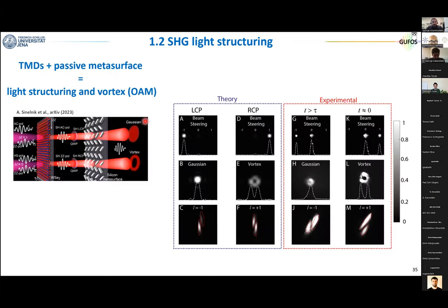And it turns out, this is something that we did in collaboration with Isabel Staude in Jena, that if you have an ultra-fast half-wave plate, that is our TMD in the nonlinear optics regime, and you combine it with a passive metasurface, then this total optical element can be used to tune the wavefront of light. So now we can play with this device to achieve on an ultra-fast timescale beam steering, Gaussian to vortex beam tuning, but even tuning of the orbital angular momentum. So these nonlinearities of the TMDs are also very powerful if you then want to combine them for complex light structuring and light shaping.